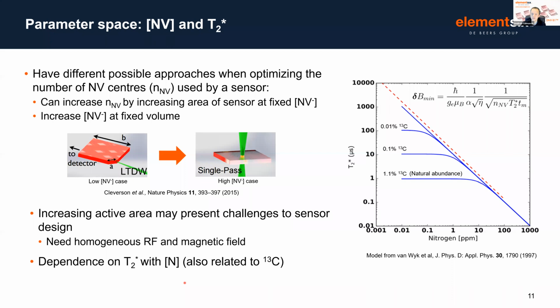The other fundamental question that we need to answer when we think about growing a diamond for this sort of application is how much NV do we want in this material? And really, there are different approaches when optimizing the number of NV centers used by a sensor. Firstly, we can increase the number of NV centers simply by increasing the area, so increasing the size of the piece of diamond that we're using at a fixed NV minus concentration. Or alternatively, we can increase the NV minus concentration and keep the volume fixed, or obviously a combination of those two things.